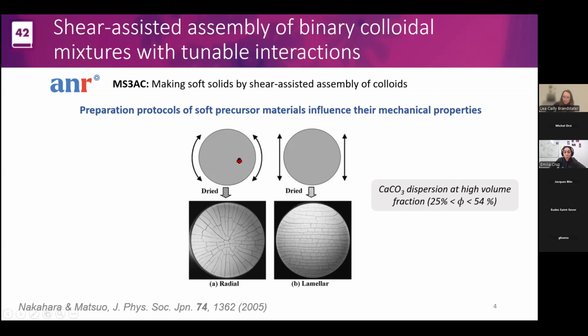We have two buckets basically next to each other of the same dispersion, same volume fraction, same solvent. But the way that we shear the bucket and then we let dry the solvent will reveal a different inner structure. So we can see it through the fracture shapes that we see here in these images. So the bucket that was stirred in an oscillatory way, for example, reveals this radial inner structure somehow.